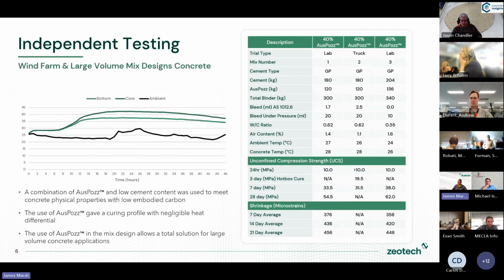Final slide on results here. This is results from that hot box test. You saw the picture in the first slide. What we did here was the mix design here, we had 180 kilos of cement, 120 of AusPozz in those two. We increased it a bit here. So it's 40% replacement in each case. We just changed the amount of binder there. This is a typical design that was given to us for wind farm bases. So we try to base our work on this wind farm design, but it's applicable to any large volume pours.